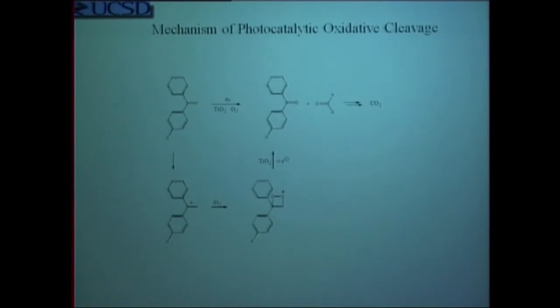But subsequent work allowed us to demonstrate, both theoretically and by experiment, that formation of the radical cation that is immediately below the starting material is trapped by oxygen to give a four-membered ring in which those two oxygens constitute two of them, what we call a dioxetane. The dioxetane as a radical cation is reduced and split, and one gets the two products that are shown above, benzophenone and the corresponding aldehyde.